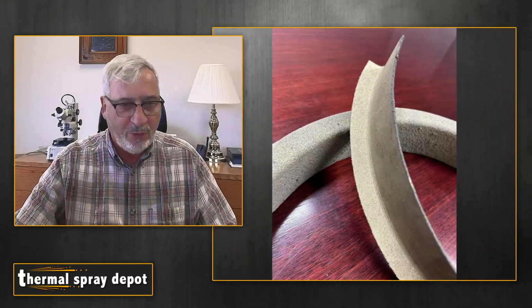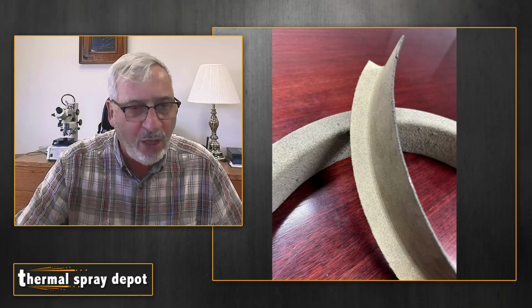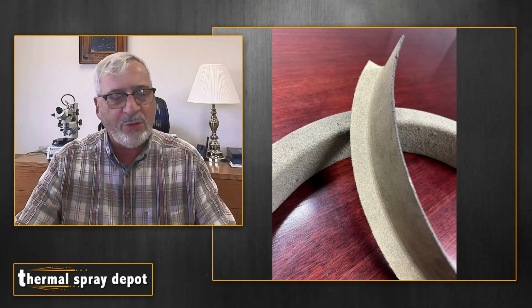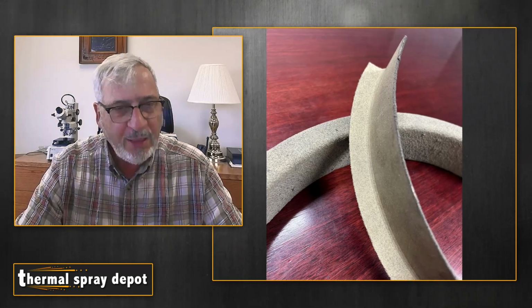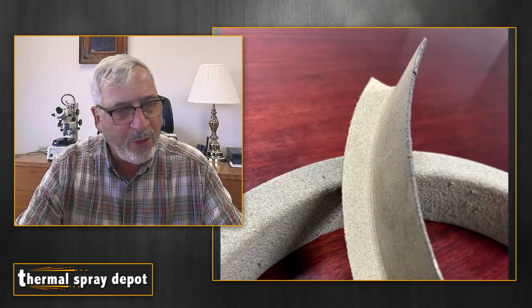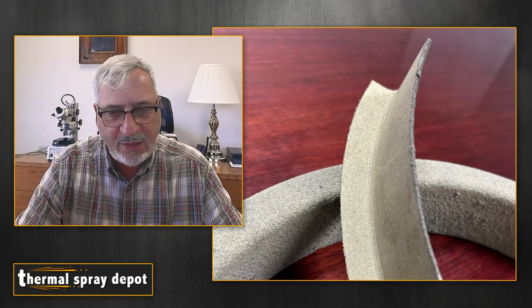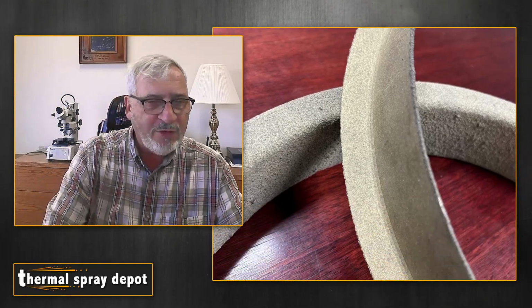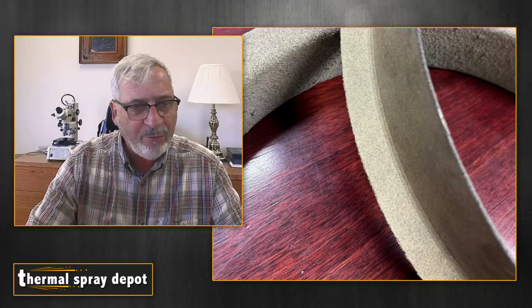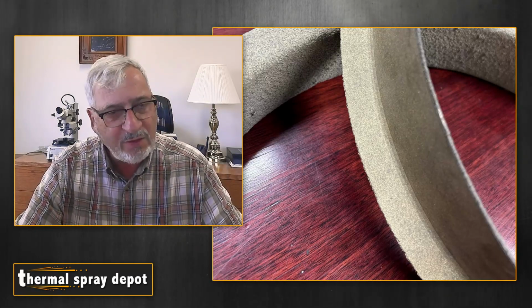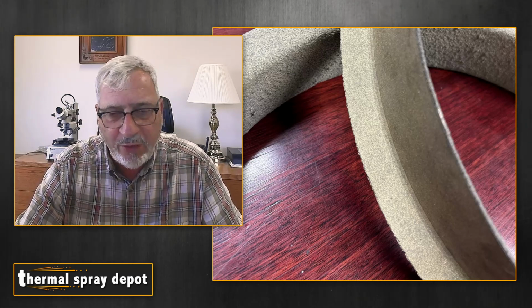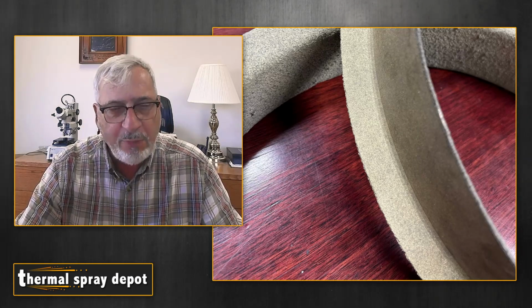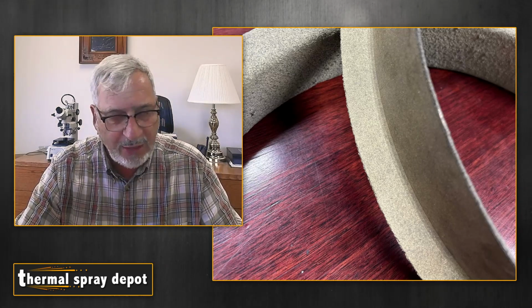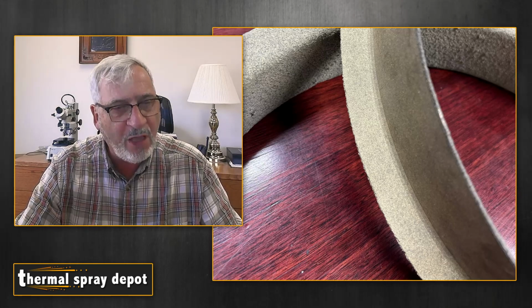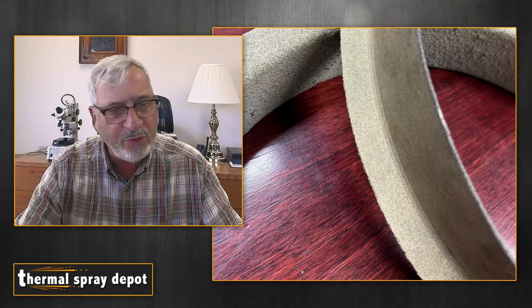Now, this is a popped coating, and it's going to be a similar cause. In this case, this was a coating that was put on an inside diameter. And what we see here, the upper part of the picture, is the inside radius that they were thermal spraying. And the part that's closer to us is the other half of this coating. So this coating was applied to this inside diameter, and it actually popped off before they even went to do the machining. It popped off after they were done spraying it. And we'll go into a couple of common causes for that, but one of them also could be surface preparation.